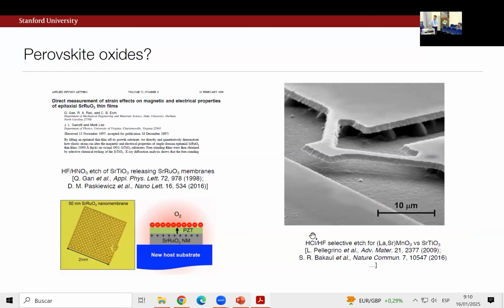Another fairly interesting and well-developed set of notions is coming from starting perhaps this paper. A group in Italy that's been thinking for quite some time of making something like MEMS-like devices with oxides. And so in this case, again, using a selective etch between manganites and strontium titanate. You can see this undercut etch and thinking about how you can start to make mechanical systems in this way. And subsequently, also very interesting work coming out of the Berkeley lab along these lines.